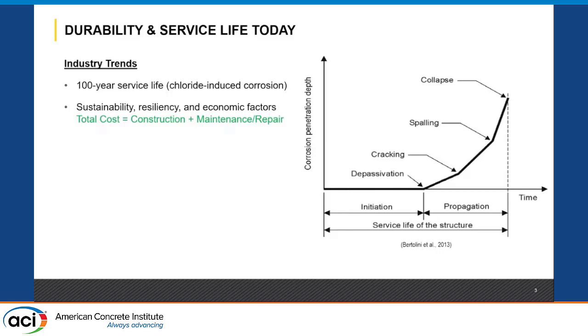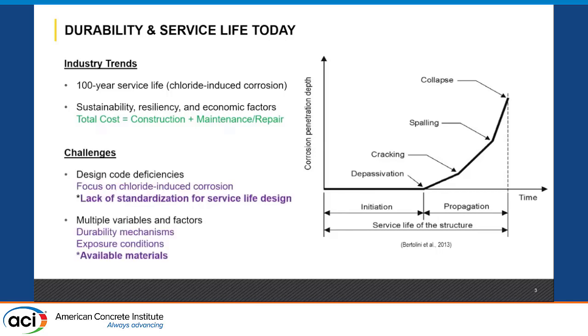And basically, when we say that it's going to last 100 years, we are talking about protecting it from chloride-induced corrosion. On the right is just a very simple chloride corrosion model of when initiation happens, when damage happens, cracking, propagation, and eventual collapse. The challenge is that there's no real specific design guideline or specification on how to get to 100 years. This is where the wizardry comes in.